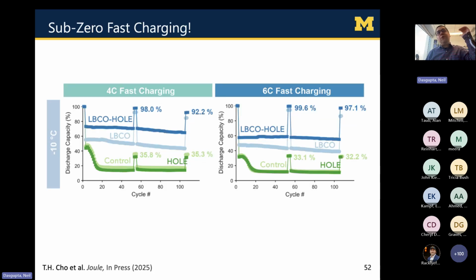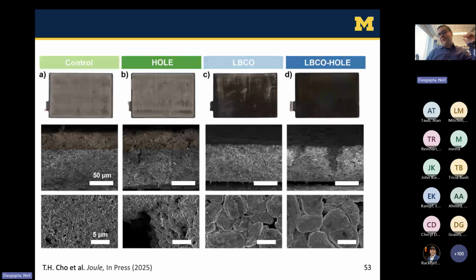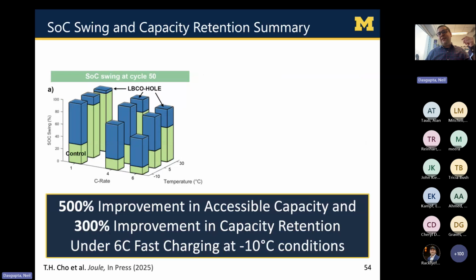Not only that, we can do 4 to 6C fast charging at temperatures of minus 10 degrees Celsius without lithium plating, which is really unprecedented in the literature. And we can do this while maintaining thick electrodes without sacrificing energy density. And we show in that paper we can eliminate the lithium plating. So I'm out of time.